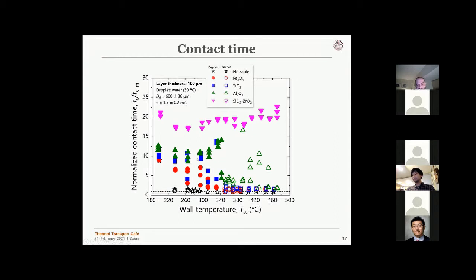If you just focus on one particular case, let's see, the green triangular data, if you have a higher wall temperature, then you will have shorter contact time because you have film boiling regime. And if you lower the temperature, then you get longer contact time because the droplet stayed in contact with the surface.